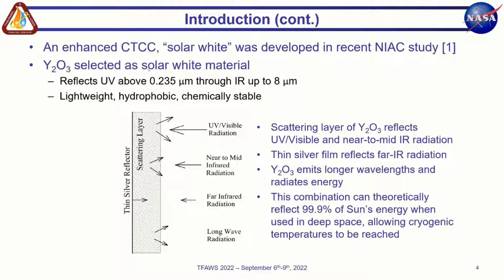The picture here shows the solar white coating, which is made up of a thick scattering layer of yttrium oxide on a thin silver reflector. The scattering layer is able to reflect the UV and visible radiation, and also most of the near to mid infrared, while the far IR is reflected by the thin silver reflector. For the long wave radiation, the scattering material basically emits and radiates that energy, and that provides the cooling. The combination of this scattering layer and thin silver reflector can theoretically reflect almost 100% of the sun's energy when used in deep space. And this will allow for cryogenic temperatures to be reached in deep space applications.